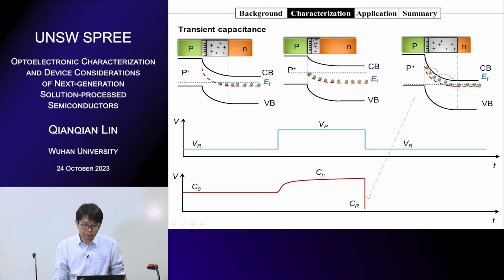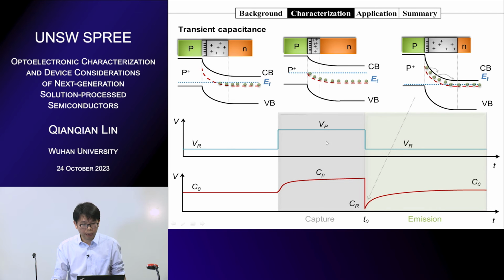Then slowly the carriers go to the Fermi level, and you will have a decay back to the initial value of capacitance. So these are two processes. One is called the capture process, to fill up the trap states, and the second step is to record the emission process of the trapped carriers. So if you can fit the curves, we can get the information of deep trap states.